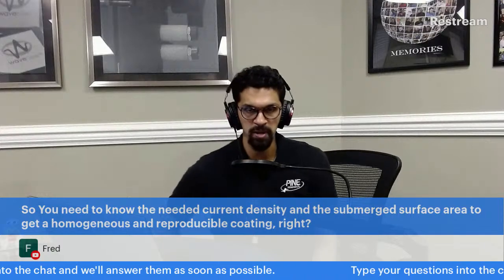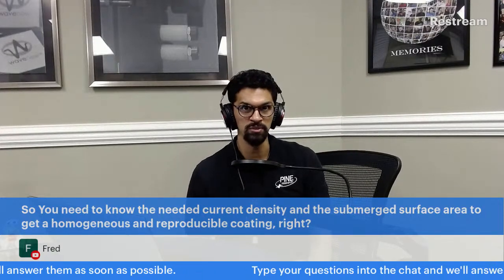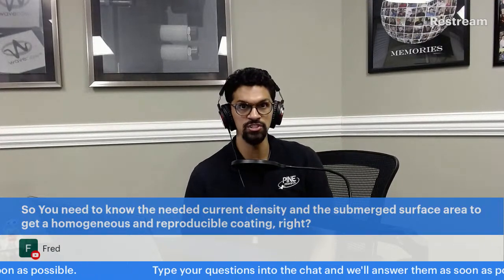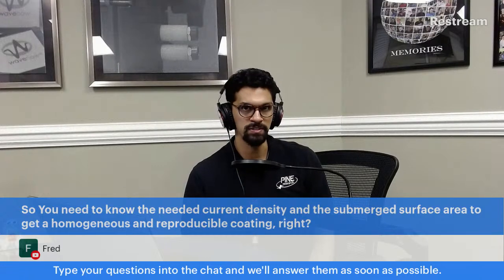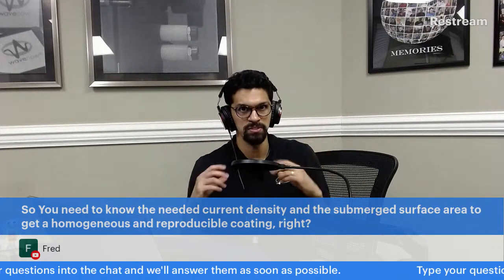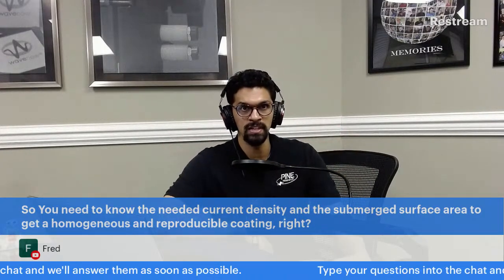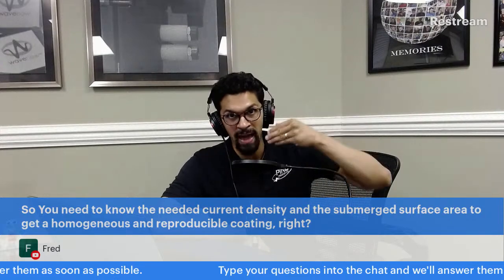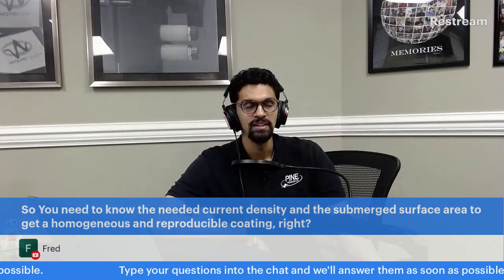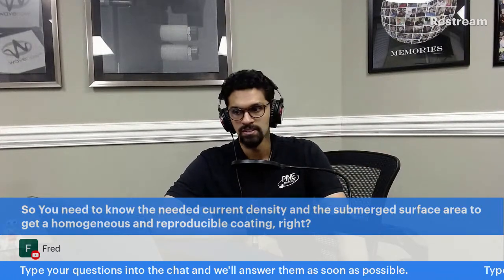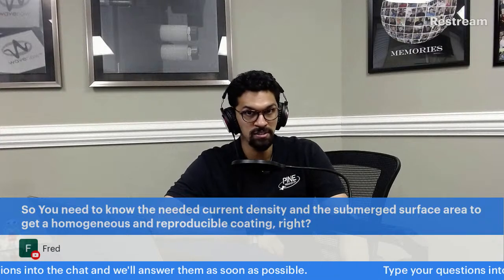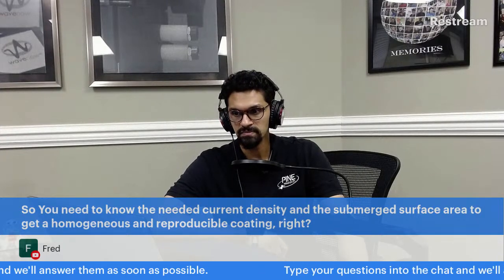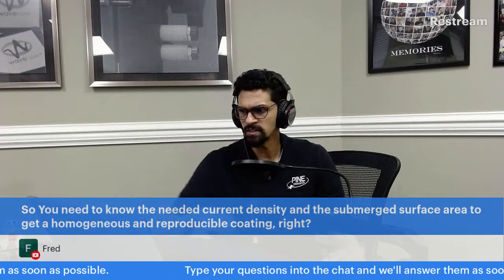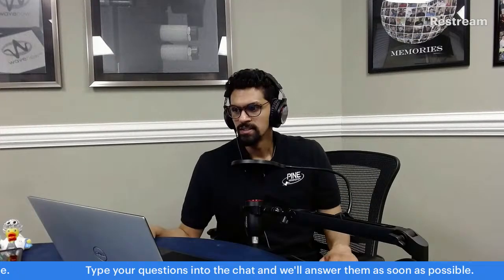While it usually doesn't affect most experiments, if you're doing large area coatings, the position and geometry of the counter electrode, kind of the field lines between the counter and working electrode, how the current physically passes between those two, can affect how it's coated. So I'd even look at your counter electrode as well to help with understanding reproducible coatings.